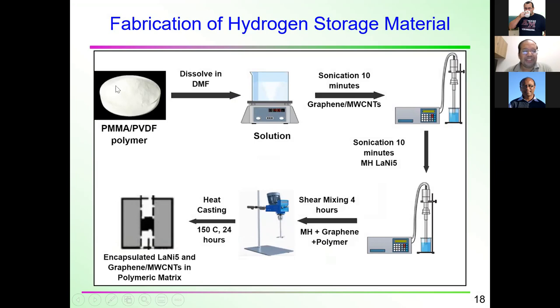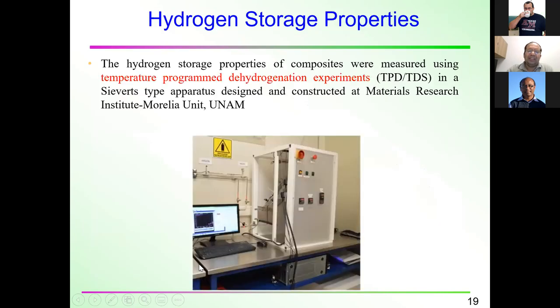I started with PMMA and PVDF, some polymer, and dissolved it in DMF, and then sonicated it for a certain time. I added graphene or other carbon-based material, did probe sonication, and then added lanthanum nickel metal hydride in that solution. Then I shear mixed it for four hours to make sure all the metal hydride and all the carbon particles are uniformly distributed in the solution. Then I heat cast it at 150 Celsius for 24 hours. These are the encapsulated lanthanum nickel and carbon-based metal hydride polymeric composite. It's a composite material.